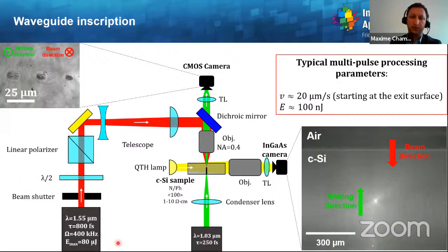So to answer this, experimentally, we have another setup relying on 1.55 micron wavelength at around 0.8 picosecond duration. Then classically, the beam is focused in the bulk of silicon. We have also one transverse microscope here represented, relying on white light emission and detected with an objective lens, a tube lens, and an InGaAs camera. Besides, we have another microscope here in green for positioning the focus with respect to the entrance surface, as you can see here.